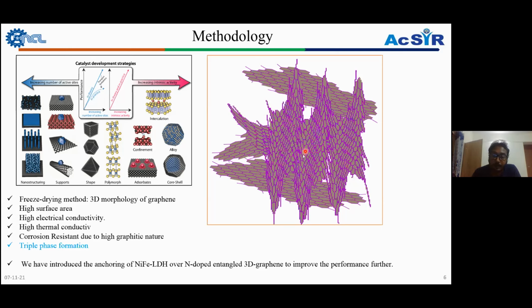So here from the 3D structure, a uniform porosity is there, which will be helpful for better electrochemical performance. So we have applied the freeze drying method to form the 3D morphology, the 3D graphene. Another important thing is that the individual sheet can act as a metal anchoring site, and there is a porous channel which could help to give a better electrochemical surface area. Graphene also has high electrical conductivity and thermal conductivity, and due to the presence of the graphitic structure of the graphene, it helps with better corrosion resistance, which further helps triple phase formation during the electrochemical performance.